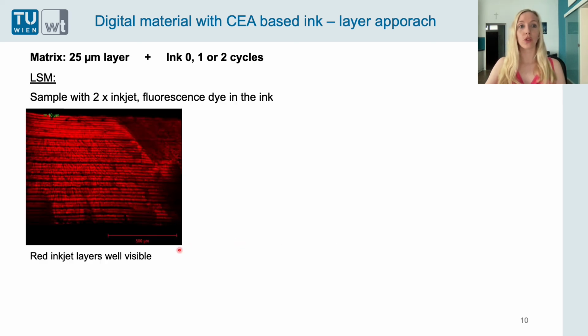So we also looked at the structures via LSM measurements. Therefore we added a fluorescence dye to the ink to make the layers visible, and you can see here in the pictures the red inkjet layers are well visible. There's not always the same distance between the layers, but it looks quite nice.